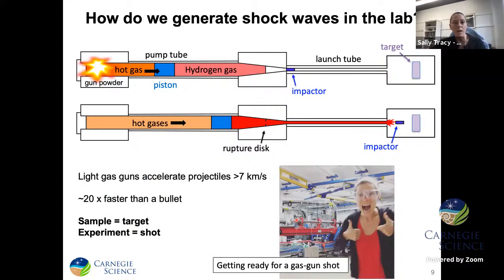So how do we go about generating shock waves in the lab? One means of doing this is using an instrument known as a two-stage light gas gun, which is shown schematically here. With this sort of cannon-like device, we can accelerate projectiles to very high velocities, up to around 7 kilometers per second or so. And so that's around 20 times faster than a typical rifle would fire a bullet, so very fast.